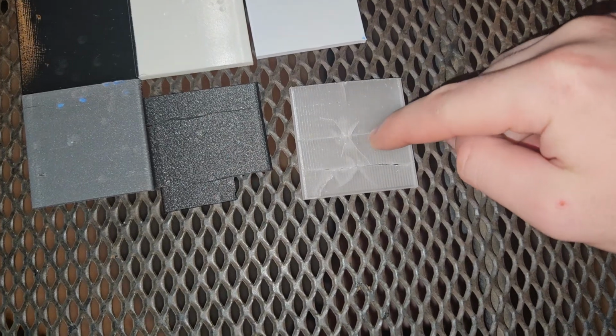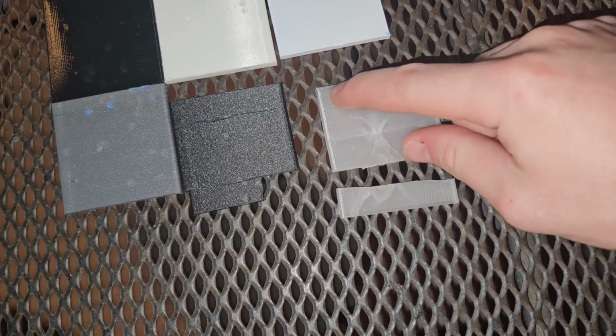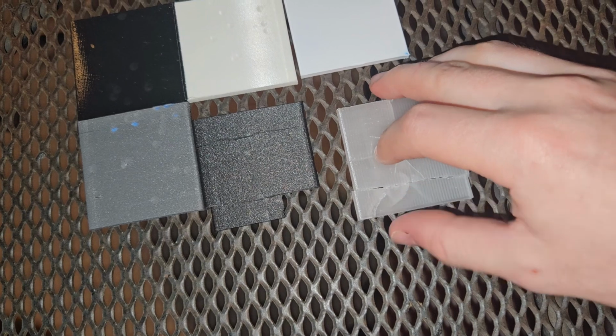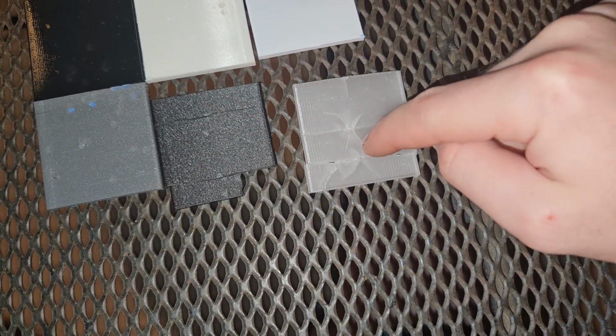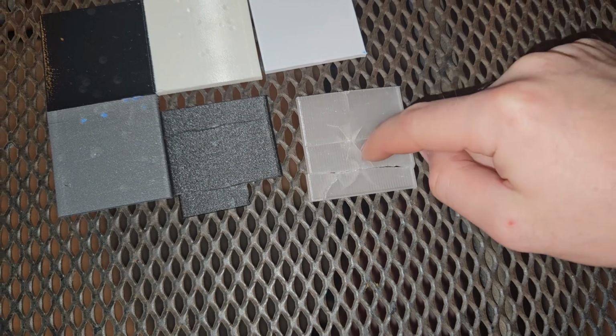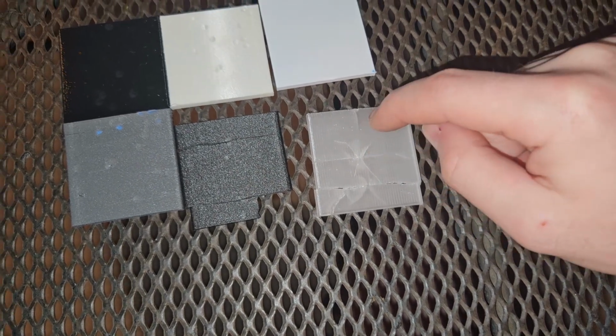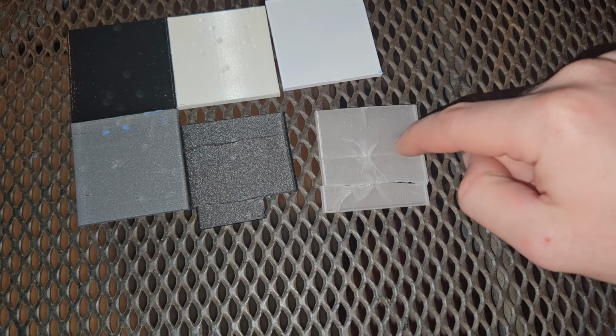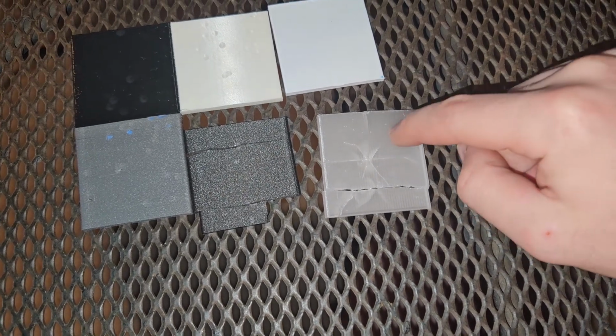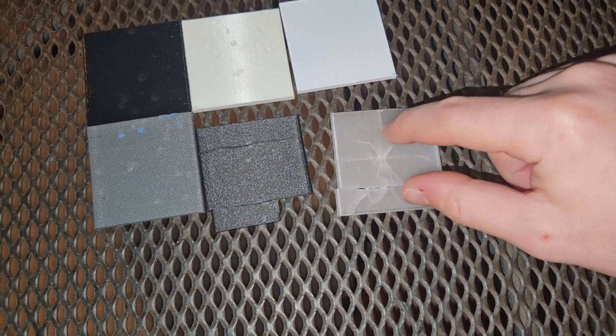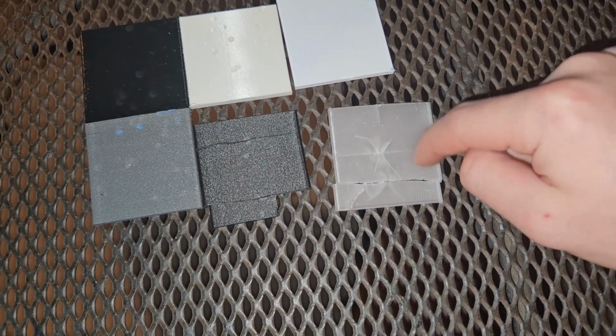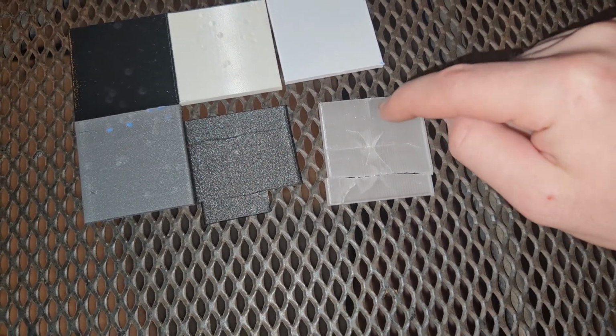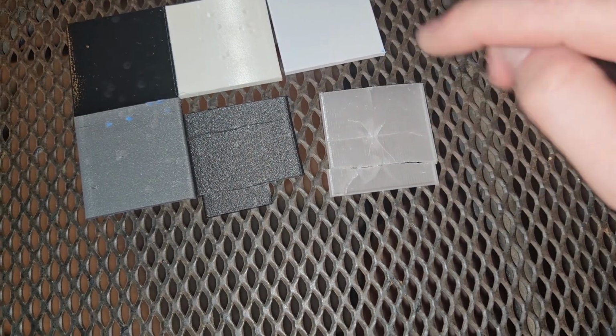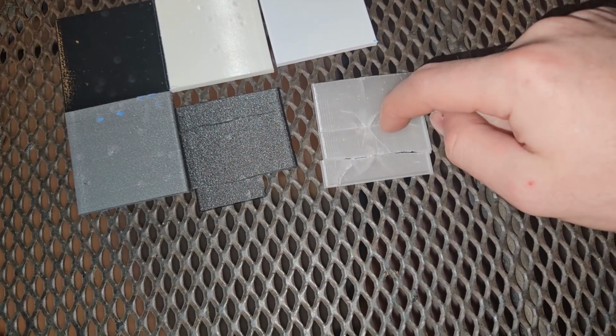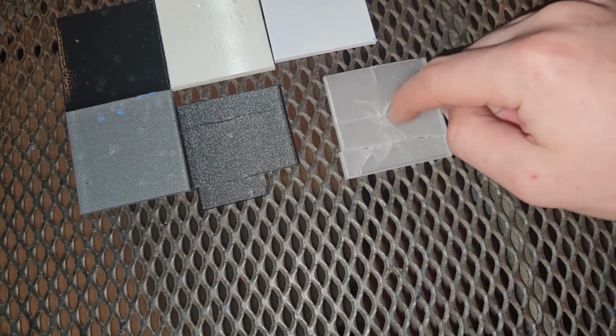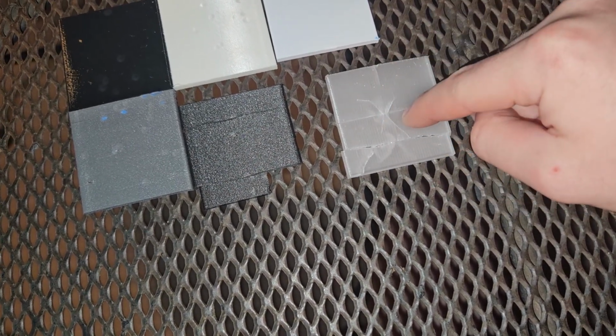I believe on the first shot we cracked it, and it just broke and shattered. Honestly, I did some testing earlier using same brand Overture PETG, but this one was black as opposed to the clear, and honestly the black PETG fared quite a bit worse. I'm curious what color additives they use and if they result in strength issues, because when I shot the black PETG, it shattered. I mean, it went into dust, millions of little pieces. You were not going to recover it. This one fared quite a bit better, but still clearly not well. This is clearly too brittle for this. This is also obviously why we don't use it on real firearms.